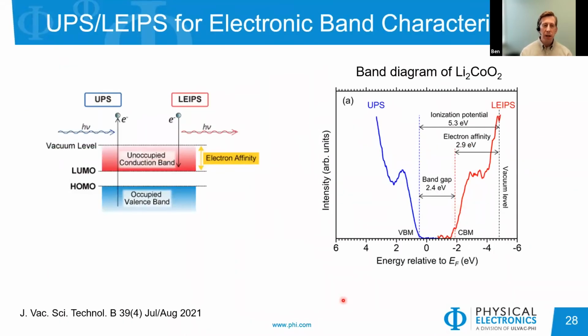Just to show in a little more detail how UPS and LEIPS work together. Again, as I mentioned, UPS is similar to XPS in that we use photon irradiation to generate photoelectrons from the valence states. With LEIPS, we are adding electrons with a given kinetic energy, and those will fill in the unoccupied conduction states and generate photons. And so you will end up with a figure something like this. We can look at the UPS data and determine the valence band maximum, which will help us understand the ionization potential. We can also, from the LEIPS, get a photon signal where we can find the conduction band minimum, which allows us to identify the electron affinity from the vacuum level. And we can combine those together for the band gap.